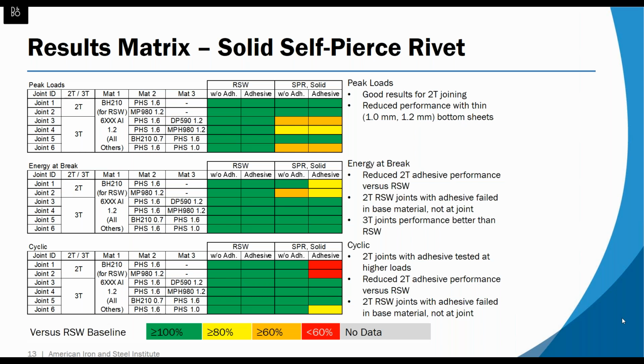I want to point out here that because we had adhesive in this joint, we used a much higher force than we did in the non-adhesive joints. So this doesn't mean that adding adhesive made the joint perform worse, but we had to increase the load substantially to get a failure. So it's only underperforming compared to resistance spot weld with the same load.